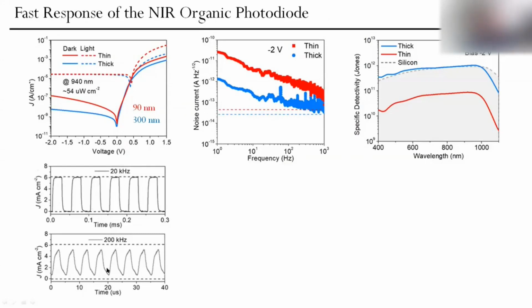So we have shown the time response of these devices. In particular for the thick active layer device, you can see that at 200 kilohertz, so the frequency of the light signal we shine on the photodiode, the electrical photocurrent response barely can follow it, because we don't see the square shape of the light we shine on it. However, at 20 kilohertz, one order of magnitude smaller, we can see a very nice response of this photodiode, which shows that up to these frequencies it can operate and adequately respond to light signals.